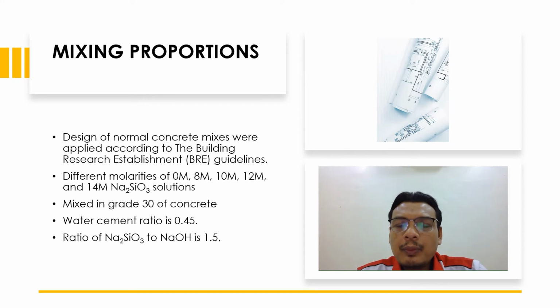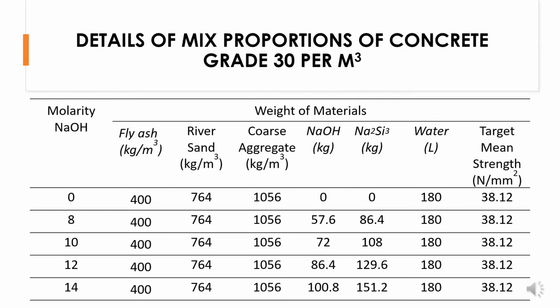This is the mixing proportion used in this research. Design of normal concrete mix will apply according to the Building Research Establishment BRE guideline. The different molarities of 0, 8, 10, 12 and 14 molarities of sodium hydroxide solution were used in this research. Mix of grade 30 of concrete was used. Water cement ratio is 0.45. The ratio of sodium silicate to sodium hydroxide is 1.5. This is the detail of mixed proportion of concrete grade 30 per meter cube.